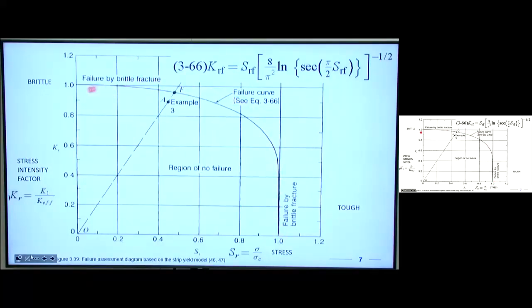Okay? So if we apply what we know about fracture mechanics and then the equations on the prior slide, we come up with this equation here, and it's this Kr, so a normalized stress intensity factor, as a function of a normalized stress, this SRF. And so that term appears twice here, and that is the x-axis down here.